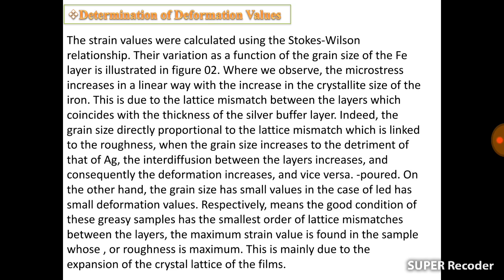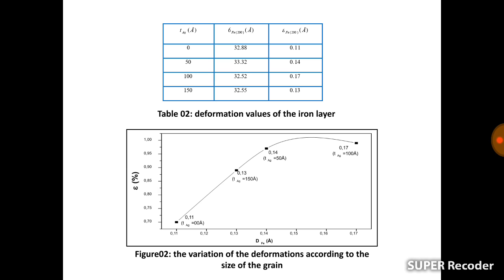Determination of the strain values. The strain values were calculated using the Stokes-Wilson relationship. Their variation as a function of the grain size of the iron layer is illustrated in figure 2, where we observe that the microstrain increases in a linear way with the increase in the crystallite size of the iron. This is due to the lattice mismatch between the layers, which coincides with the thickness of the silver buffer layer. Indeed, the grain size is directly proportional to the lattice mismatch, which is linked to the roughness.